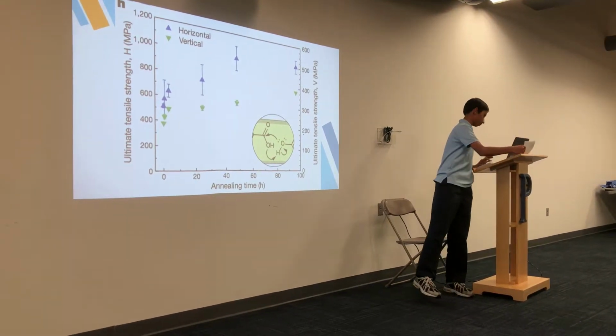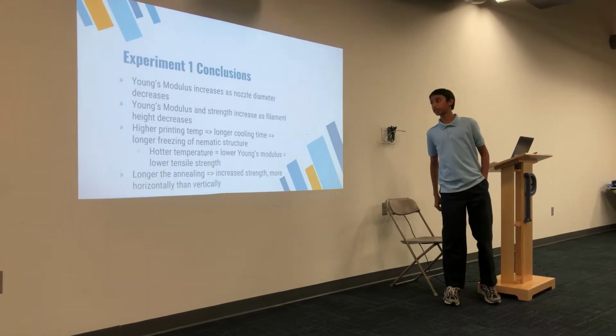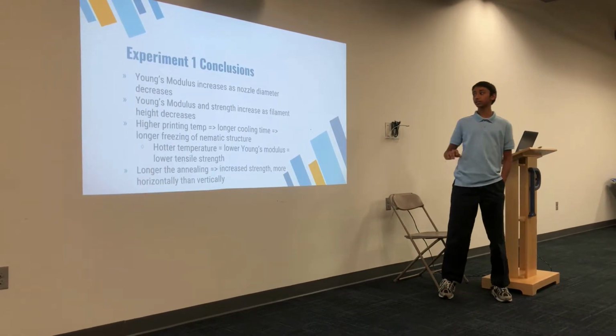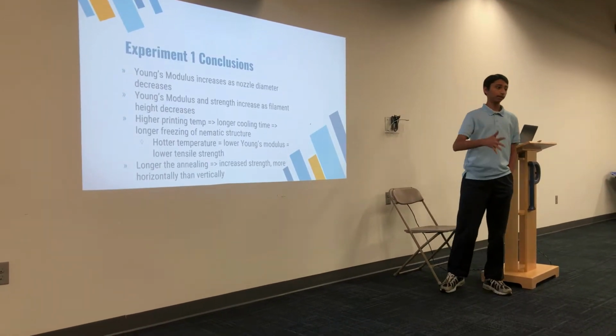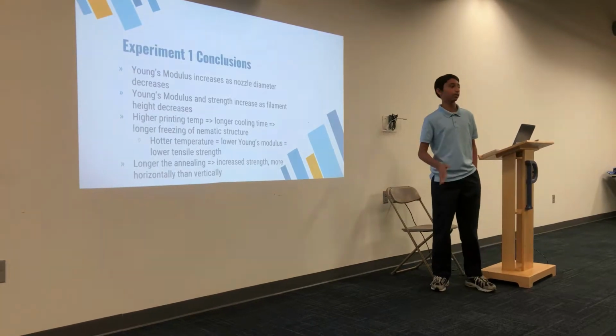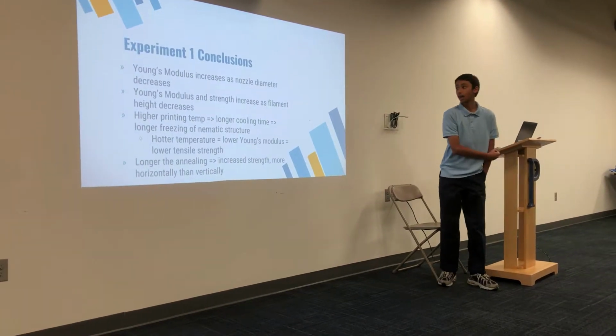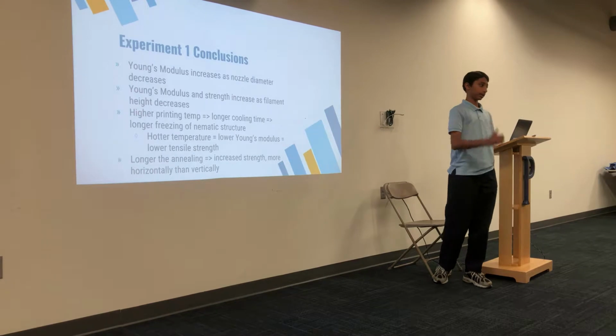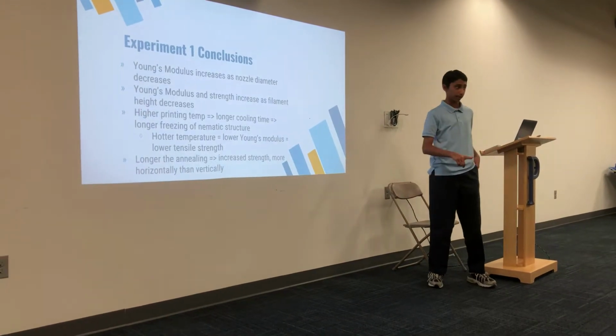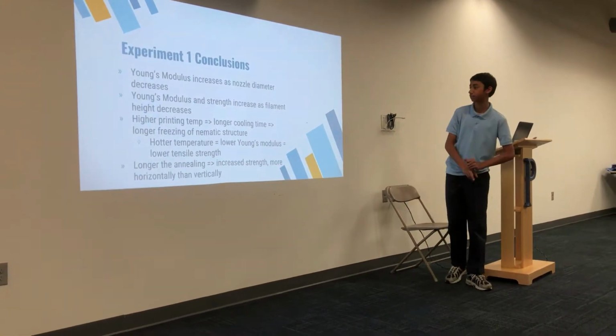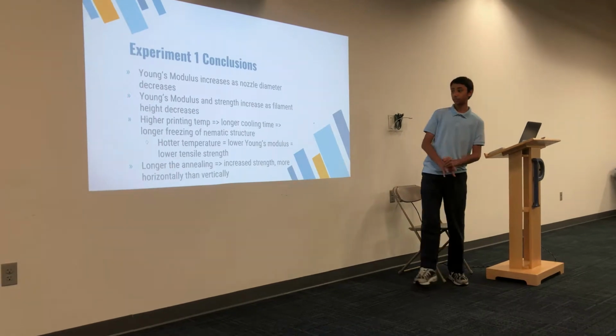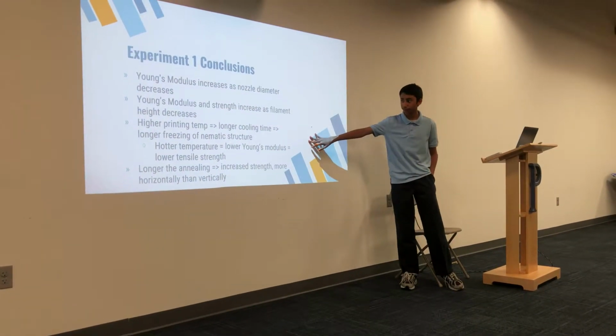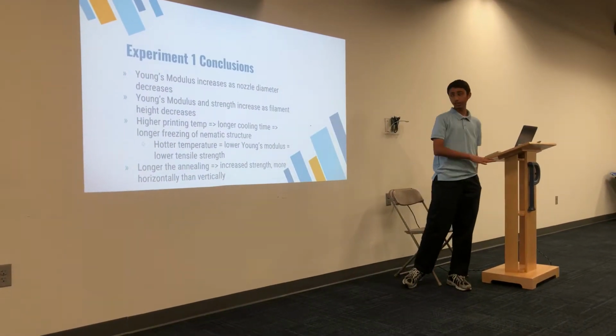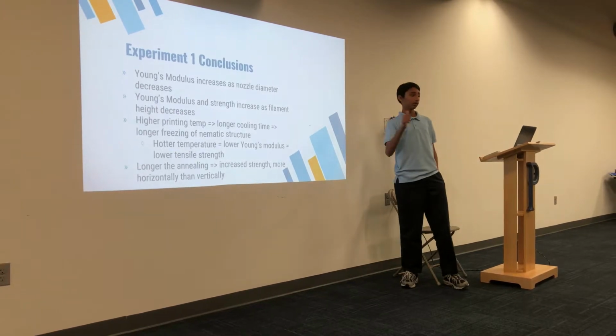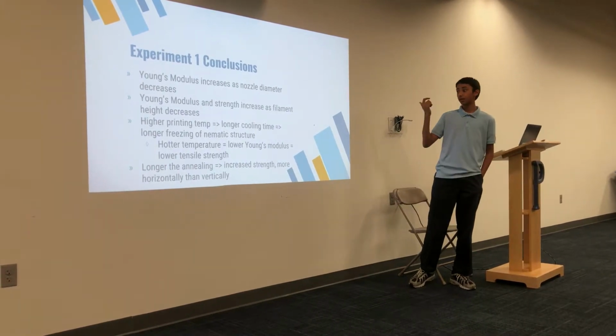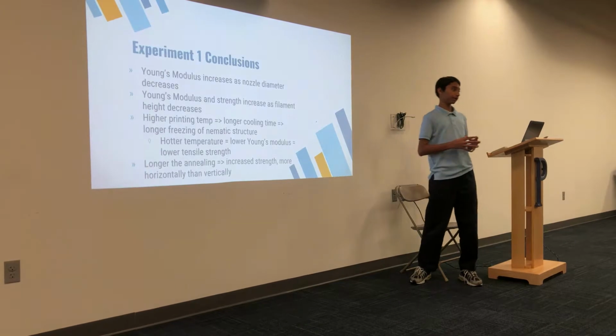Okay. So the conclusions from this experiment is that the Young's modulus is going to increase, right? The material is going to get stiffer as the nozzle diameter decreases. And the material is going to get stiffer, it's going to get stronger as the filament height decreases. They kind of go hand in hand with each other. And then the second part of this experiment with the temperature is that the higher printing temperature leads to the longer cooling time, obviously, and that leads to the longer freezing of the nematic structure.